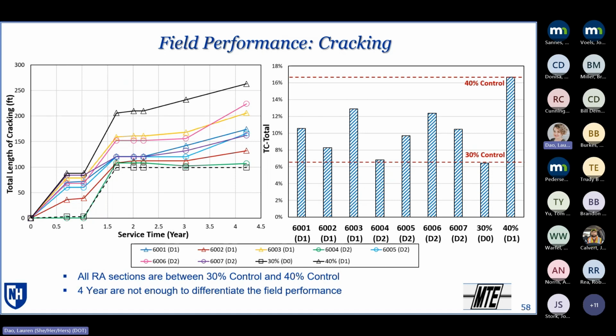So you can see from both the left plot and the right plot, the worst in terms of performance so far is that 40% control mix, the day 1, that's the top. And the best is the 30% control mix, which is the bottom one. And all the RA sections are falling right in between. And same thing when you convert that to that index value, all the RA sections are right in the middle.